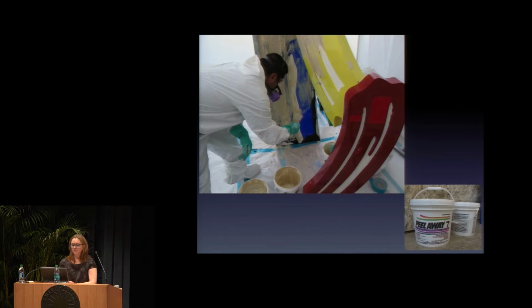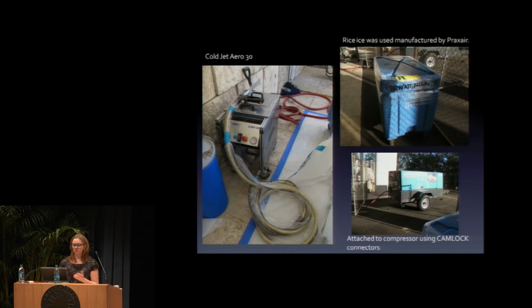So I did do a lot of testing. It's out of the range of this presentation, of different paint strippers. And we found that a Peel Away system, number 7, manufactured by Dumond, worked very well. So the first step was to apply the paint stripper, let it sit for a couple of hours, and then we used the carbon dioxide blasting using a pellet instrument.